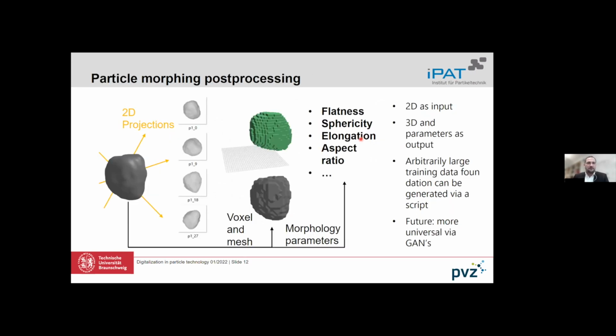There is also the possibility now to not only simulate spherical particles, we can also simulate non-spherical particles of irregularly shaped morphologies. And here we can also use the data-driven models to measure 2D pictures via dynamic image analysis or via microscopy, scanning electron microscopy.